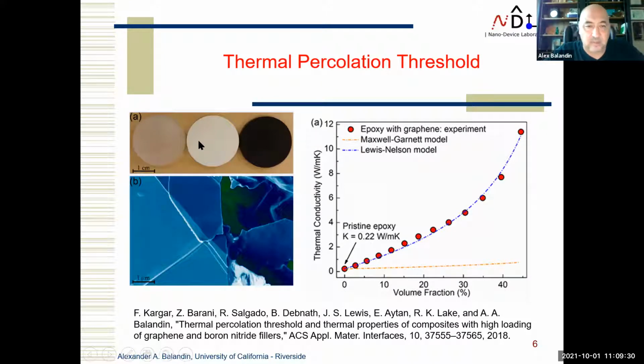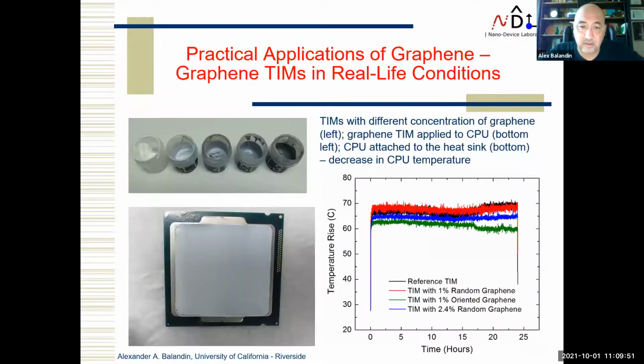And here you see these are epoxies. The white one is boron nitride, which is electrically insulating, and the black one is graphene, which is electrically conducting. But what we have found is you can achieve thermal percolation, and that is when the increase in thermal conductivity becomes superlinear, even before electrical percolation. So that's one of the lines of research here.